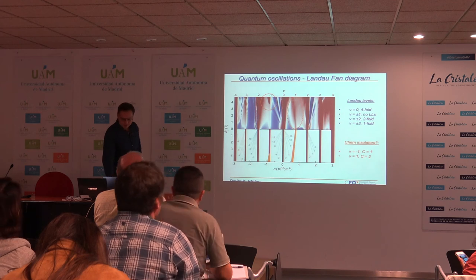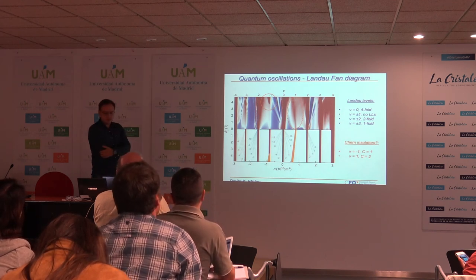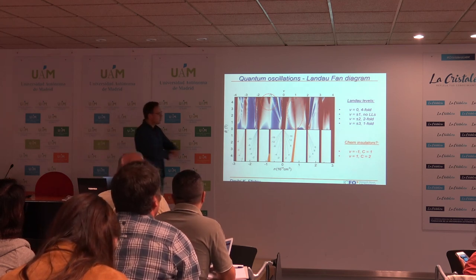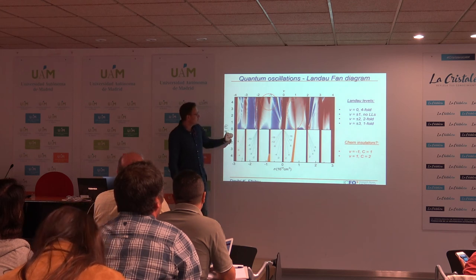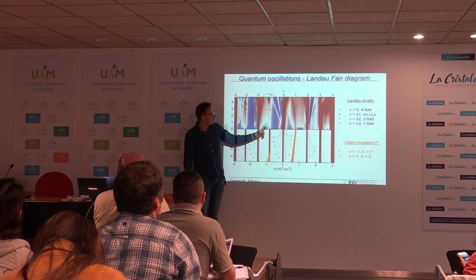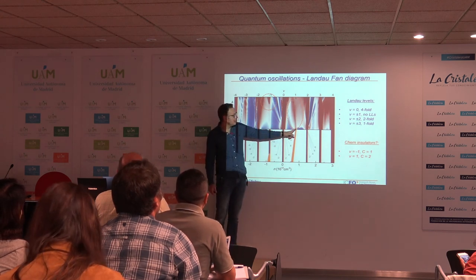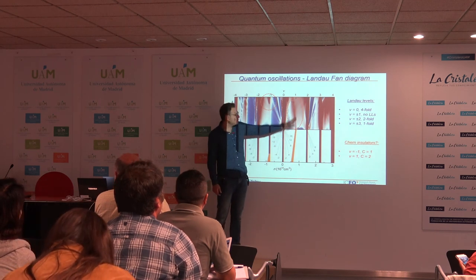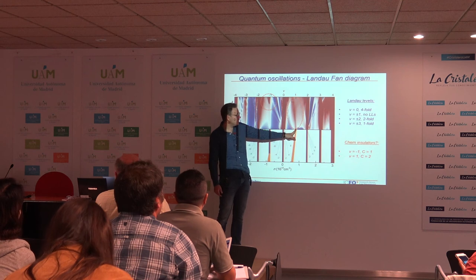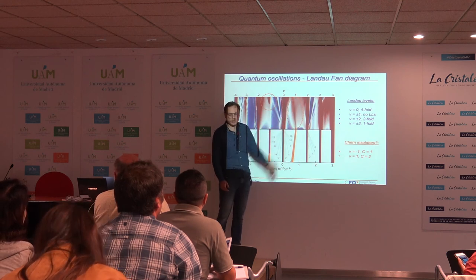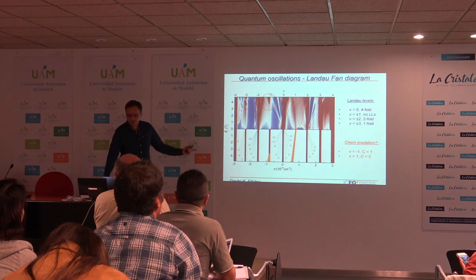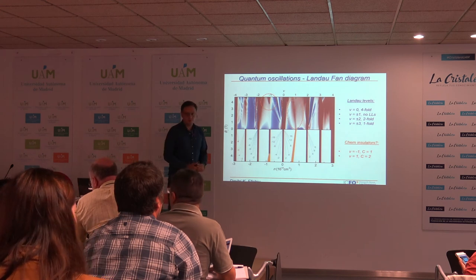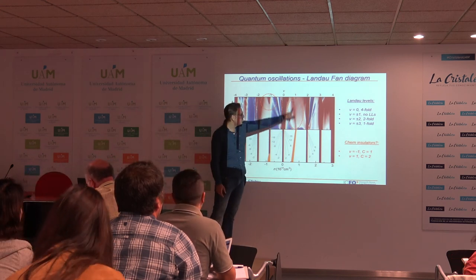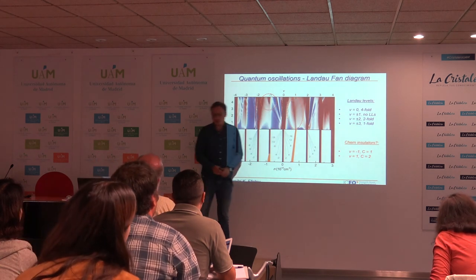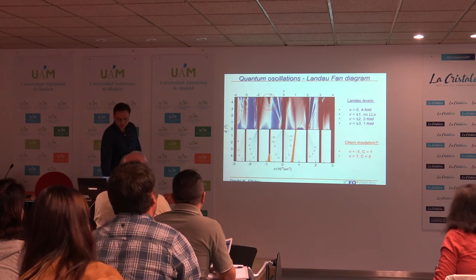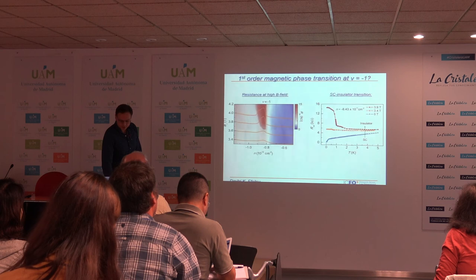Ten minutes, okay. Right. So the other thing that is really interesting about these Landau fan diagrams is that, while I talked about minus 2 and plus 2, at some of the odd integer fillings, for example here at plus 1, we don't see Landau fans. We don't see these fanning out line shapes, but we see that the position of the insulating state itself has a slope. And this slope is consistent with a filling of 2, or in other words, a Chern number of 2. So what we believe is that these states are actually not Landau levels, but have to do with some potentially topological insulating states. And I'll show more data to support this claim.